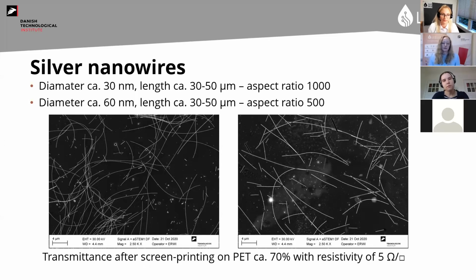So I have taken 2 examples out, and how the nano production or development actually affects both the ink formulation and the component, and how we need to be aware of it when we produce the material. So the silver nanowires, as you can see here, are 2 examples. One of them has a diameter of 30, the other one has a diameter of 60. And it's a little bit difficult to see in the pictures, but actually it has a big influence what diameter they have and what length they have. So the idea about having silver nanowires is to make a transparent component. So you still want to have a good resistivity, but you also want some transmittance through the component.